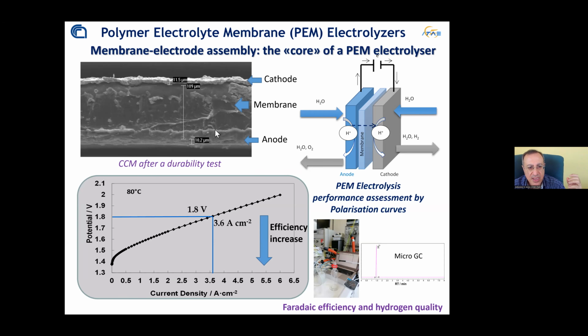This is an MEA that has been dismantled after 3,000 hours of operation. You can still see the electrode layer, the bright layer, sticking to the dark layer, which is the membrane. This is the electrode, this is the electrocatalyst, and the dark part in between is the membrane, a fully dense polymer membrane. The bright part is the electrocatalyst.